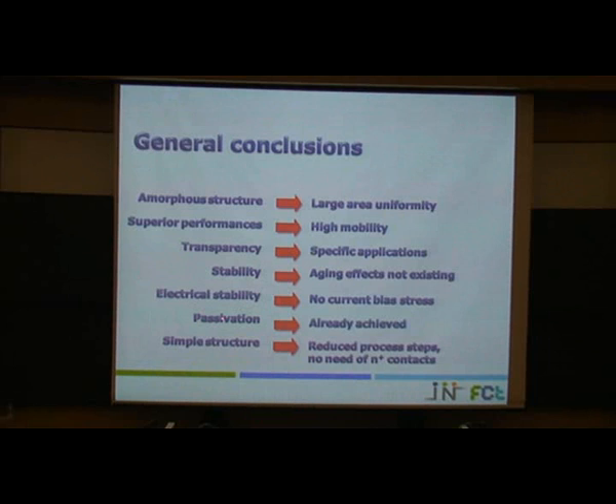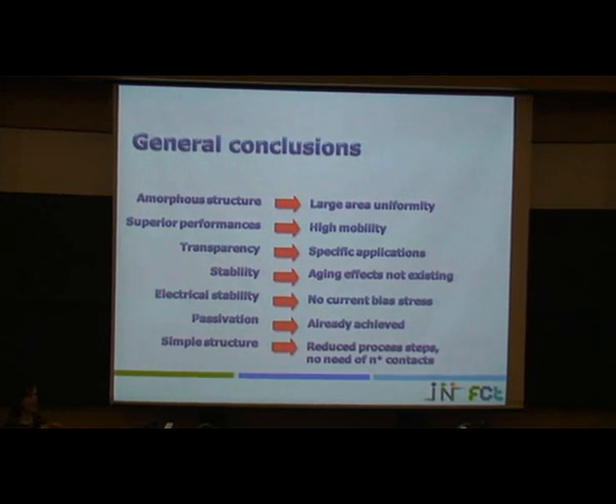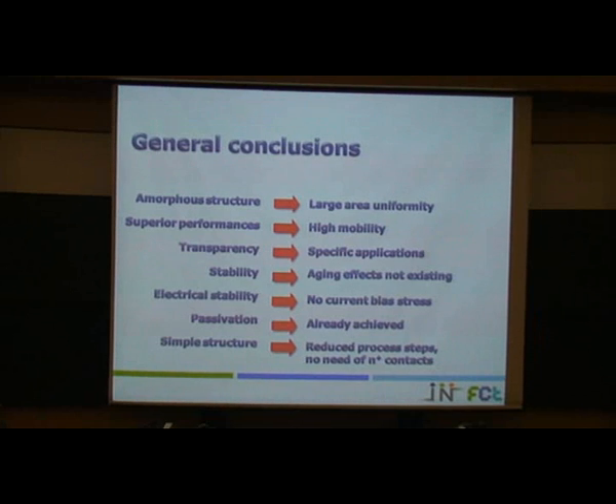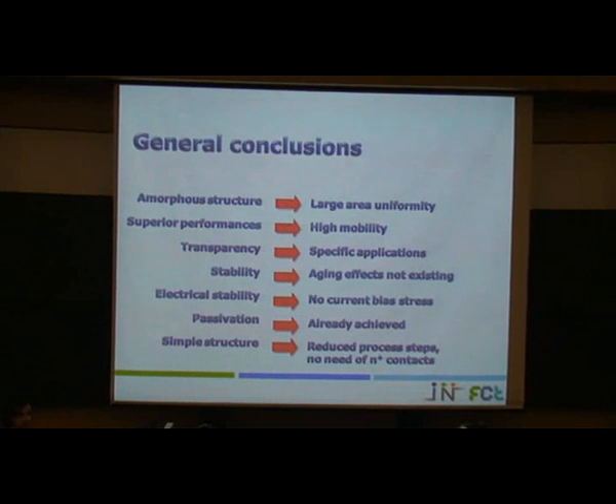They are able to be passivated, because this is important in some cases, and since we are working with oxides, in some cases when we are depositing something or when we are passivating the material, the properties are different, and this is a problem because we are making a device, but after passivation it works in a different way. And we developed a technique, and we now have a patent with Samsung related to this specific issue.